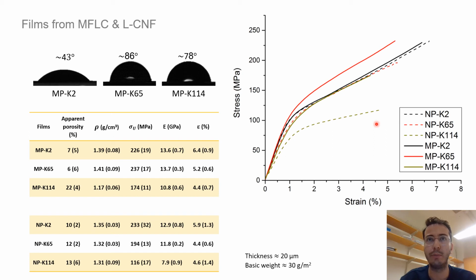One reason could be related to higher amount of lignin present in this sample, not because of only higher kappa number, but it could be because of the lignin particles which get separated from the larger fibrils, but the larger fibrils themselves in the centrifugation sediment, but the lignin particles end up in the supernatant, even from the larger fibrils. So it should have more amount of lignin, which might compromise fibril-fibril bonding.